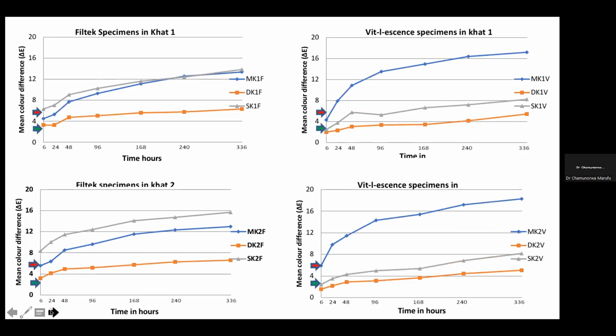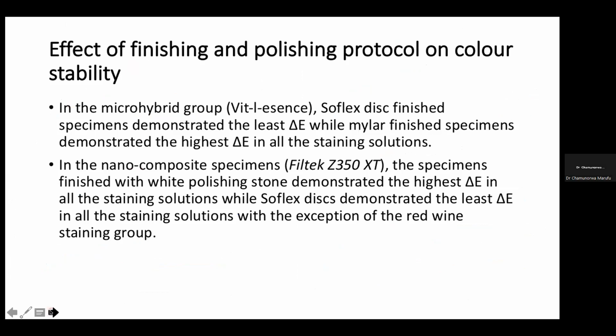And this is the same pattern shown here for the Filtek and for the Vit-l-escence composite specimens. So from these graphs, in the microhybrid group, the Soflex disc finished specimen demonstrated the least color change, whilst the mylar finished specimen demonstrated the highest color change.